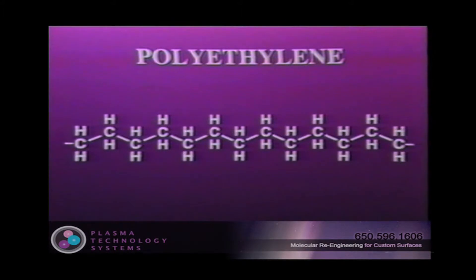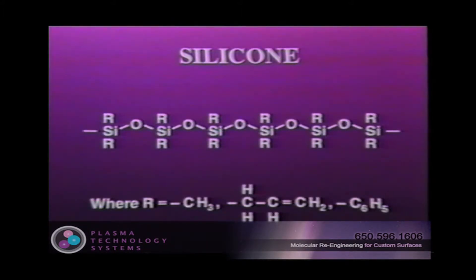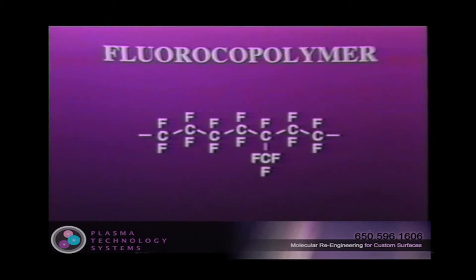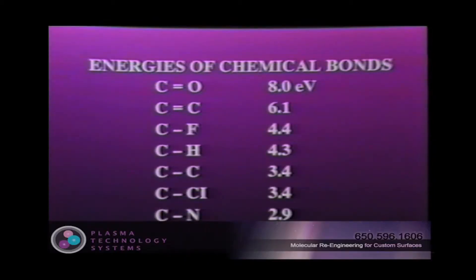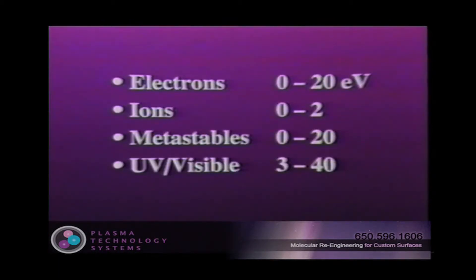Polymers usually have carbon-to-carbon backbones, although other bonds such as carbon-oxygen and carbon-fluorine are not uncommon. As can be seen in this table, the energy required to rupture chemical bonds commonly seen in polymers ranges from 2.9 to 8 eV.